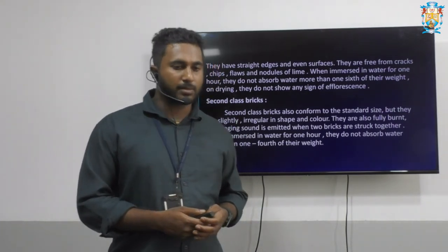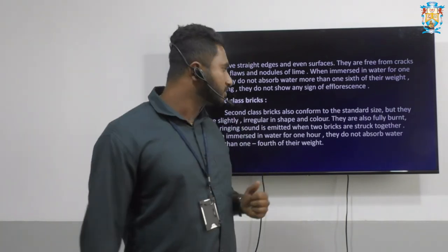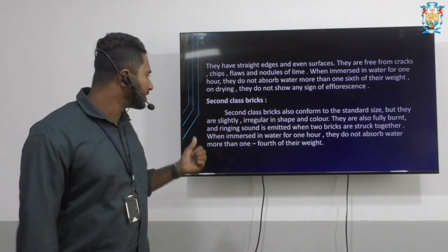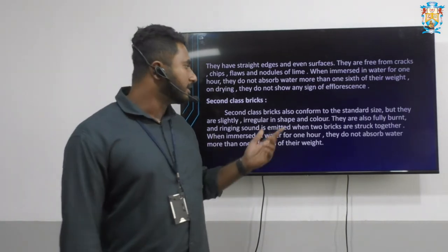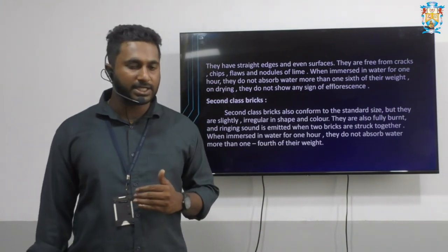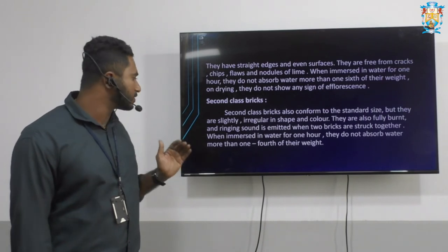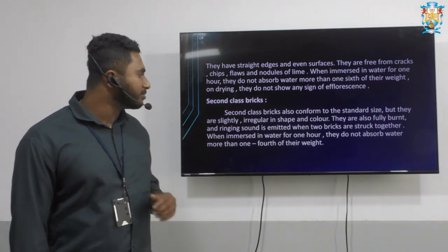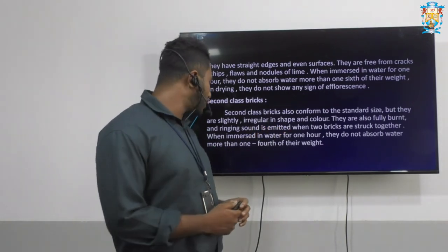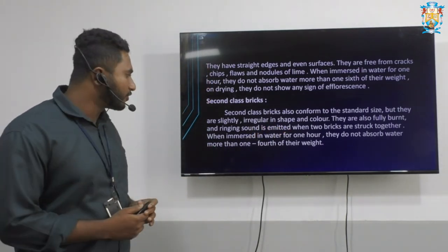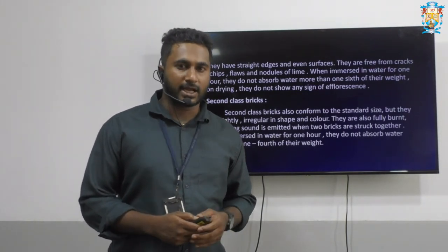Next, coming to the second class bricks. Second class bricks also conform to the standard size, but they are slightly irregular in shape and color. They are also fully burnt and a ringing sound is emitted when two bricks are struck together, but when immersed in water for 1 hour, they do not absorb water more than 1/4 of their weight. So that is about the second class bricks.